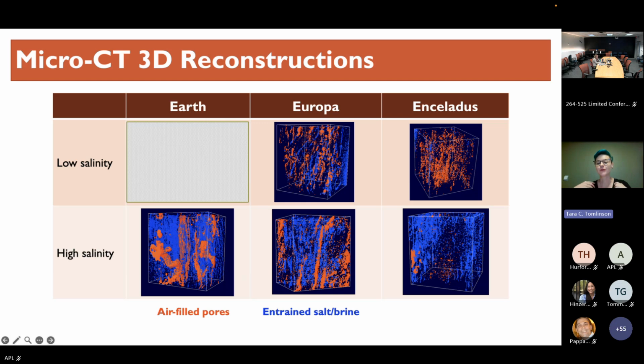Now, if we compare this to the Enceladus samples, we see something very, very different, which was really unexpected. At low salinity, we are trapping tons of little air bubbles, lots and lots of tiny bubbles, which if I had pictures, I could show you. They're like just little bubbles everywhere, but almost no entrained salt or brine. There's very, very little. When we flip to high salinity, we see a ton of entrained salt and brine and almost no little air bubbles, very few kind of scattered throughout, but still no brine channels forming like we see in our Earth ice and our Europa high salinity ice.